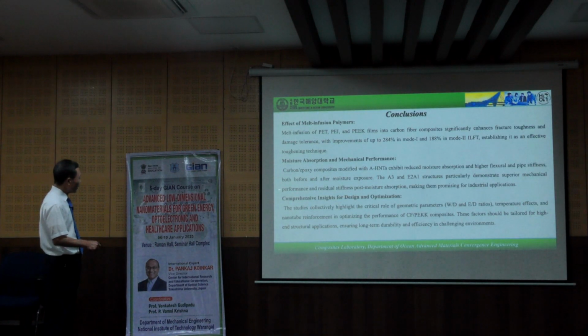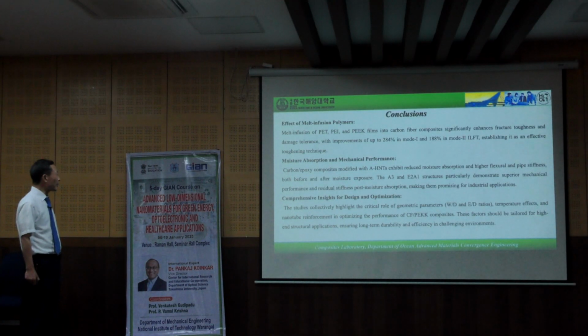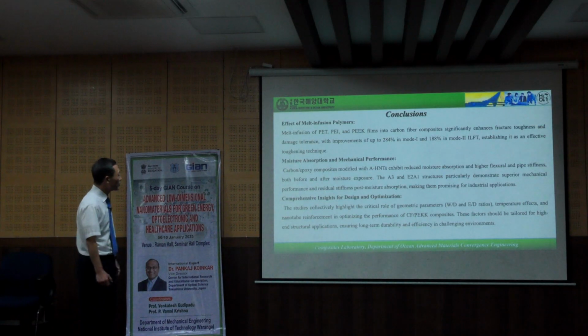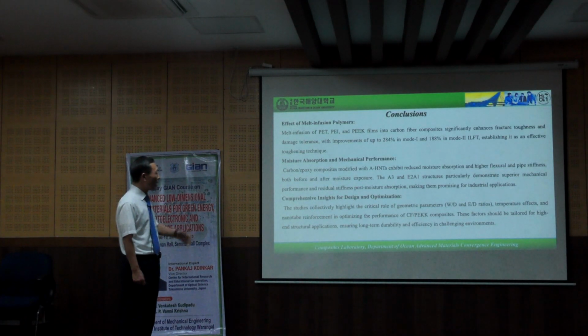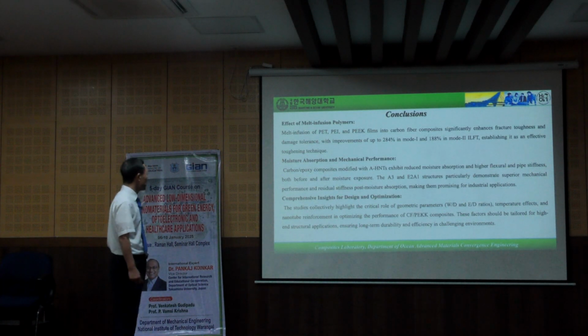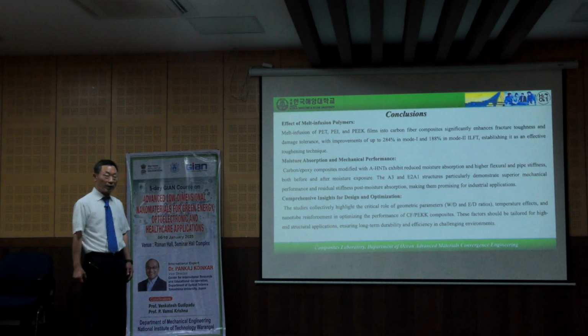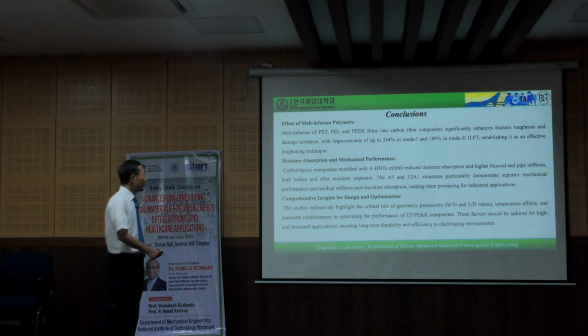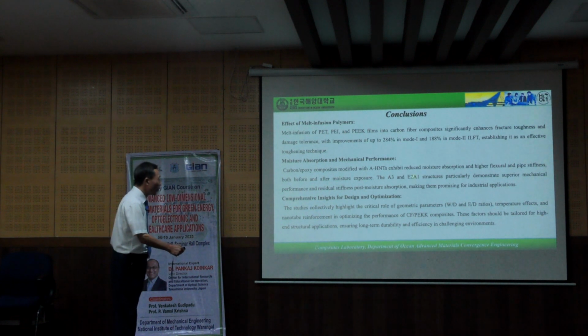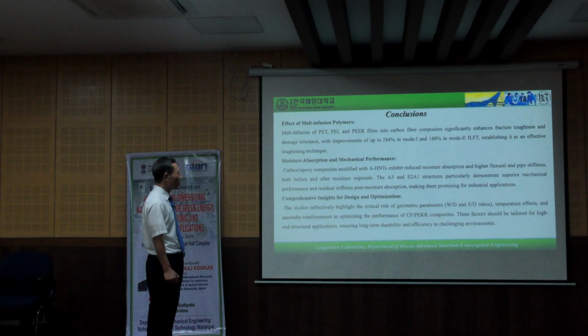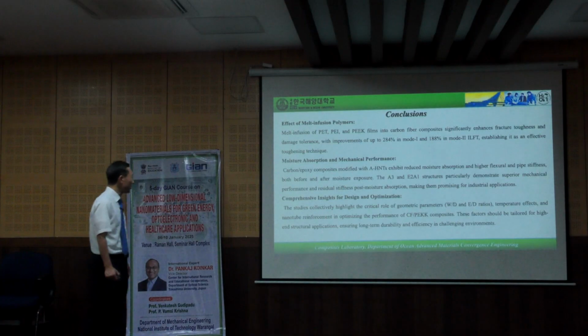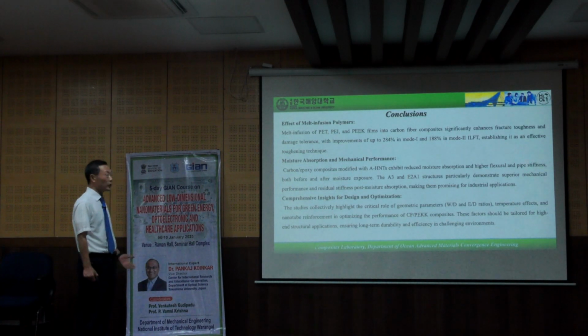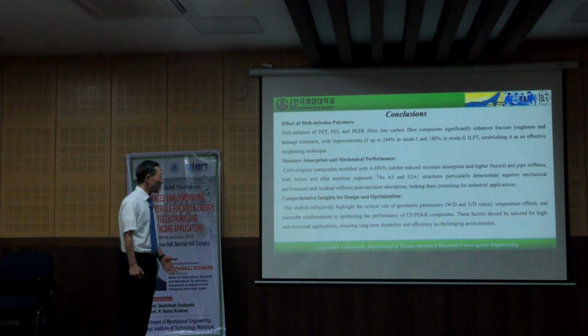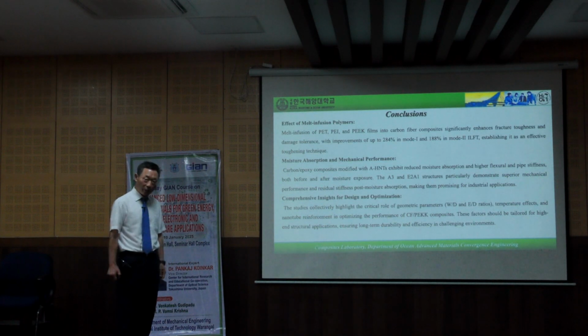The fifth one is moisture absorption and mechanical performance. Carbon fiber composites modified with amorphous halloysite nanotube exhibit reduced moisture absorption and higher fracture and flexural stiffness, both before and after moisture exposure. The A3 and E2A1 structures demonstrate superior mechanical performance and the flexural stiffness post moisture absorption, making them promising for industrial application.